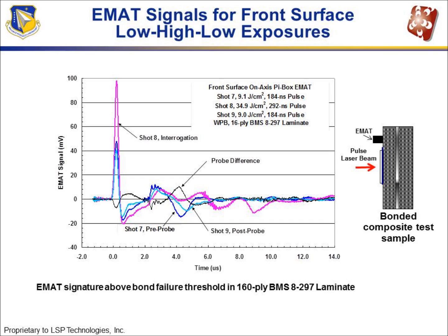This purplish trace is the main shock wave that LBI produces. That's the high energy shot. And as you compare the post-trace from the final low energy shot to the pre-trace from the first low energy shot, you can see that there is a distinct variation in the two, indicating that the bond line is weak. If it was a good bond line, the difference would be a flat line.